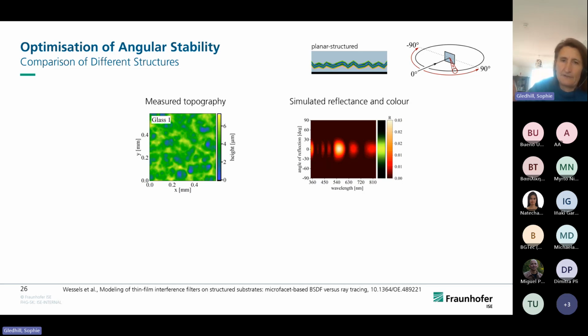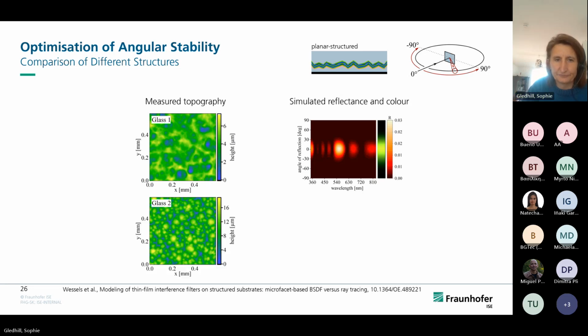What you're seeing in the graph on the y-axis is the angle of reflectance. On the x-axis, we have wavelengths, and the color constitutes the intensity. So we have a high peak at around 540, corresponding to the greeny color. And you can see with this glass measurement, we have a good angular distribution between 30 and minus 30, but when we get out to an angle of 60 to the perpendicular of the modules, we're going to perceive a much darker module.